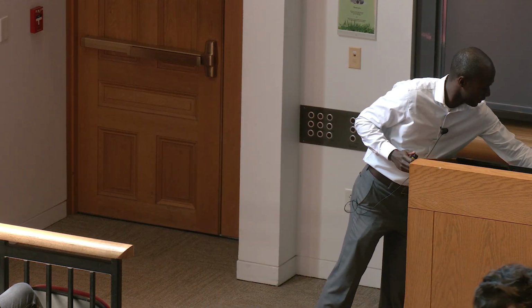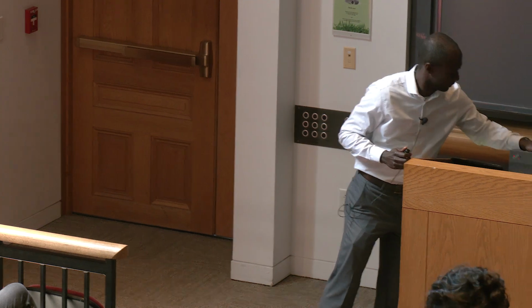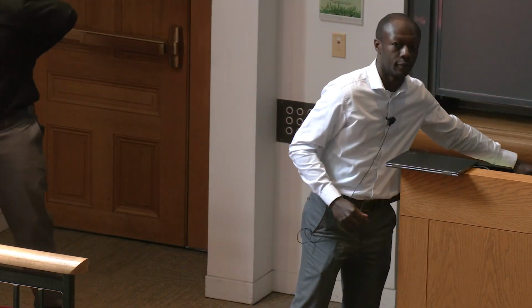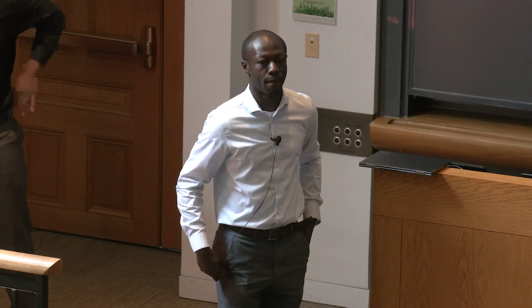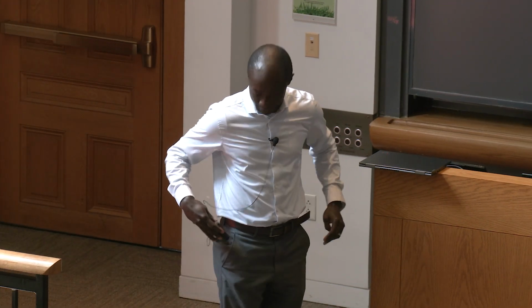It was great. Yeah, I have a question. I am not sure if you looked at the charge density on materials before. I remember you saying that when you grow your compounds, you try to be very precise and as free of defects as possible, right? But we know that charge density waves can live around the local defects, even at room temperature, way above TC. I'm wondering if there is a similar mechanism with superconductivity that can live around the defects.